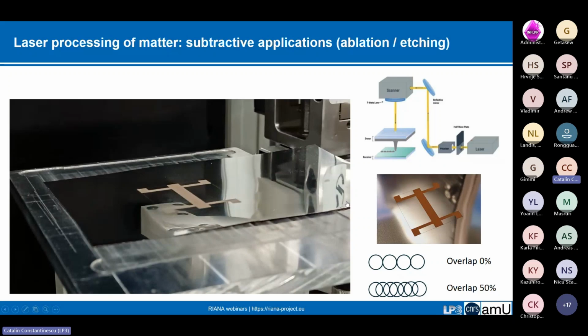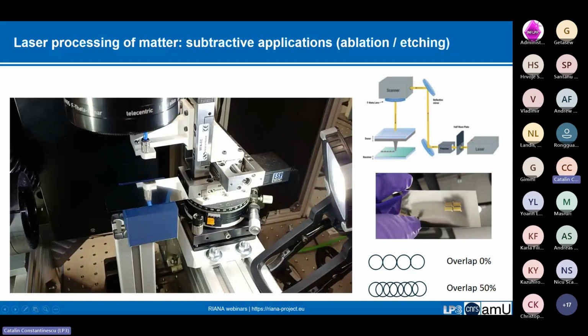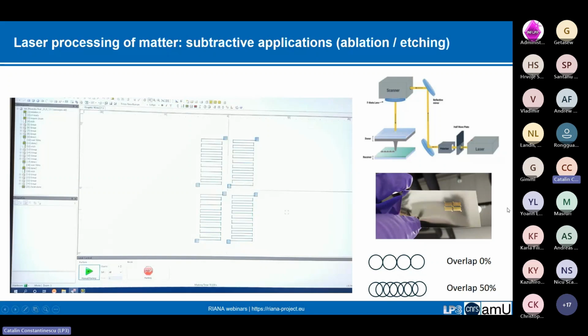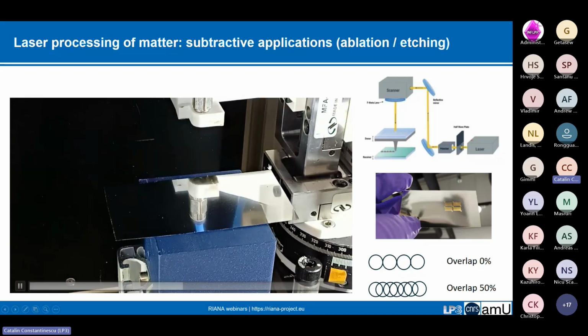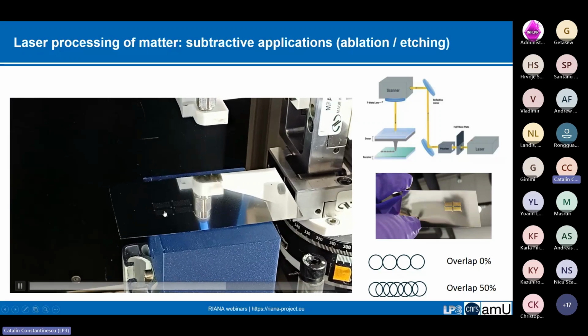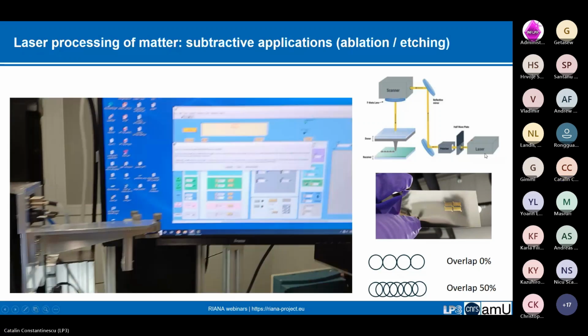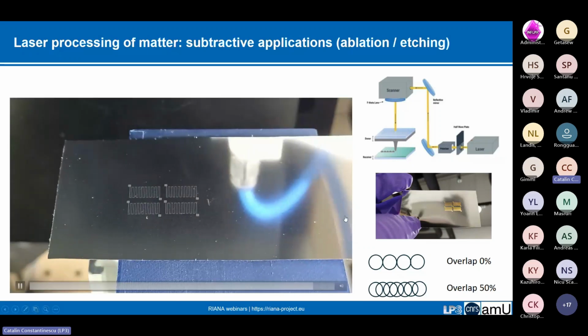This is what we did. This is just a test. And by controlling the overlap and the size of the scanned area, we can control the rastered area. And I will show you another. In here, we actually etched meanders. This is something we tried yesterday just for a calibration test, with my colleague Patricia Aloncle. So you see here the setup, the controller, and then the scanning, and you see how fast it goes. The laser has a 60 kilohertz repetition rate. So it takes very little time to actually scan.